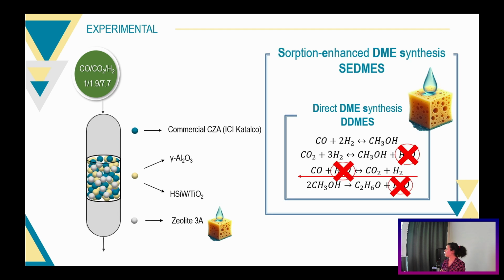The other approach was to use the very same catalytic beds, but adding to them a zeolite 3A as a sorbent material to remove water from the reacting medium. And by doing so, we would be shifting the equilibrium towards the formation of more methanol and more dimethyl ether. This process with water sorption can be found in literature as sorption-enhanced dimethyl ether synthesis, or SEDMES.